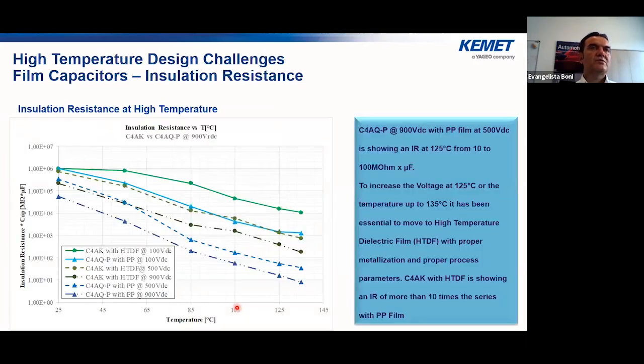Here it is possible to see also the insulation resistance behavior versus the temperature. Here we have the insulation resistance, and here we have the temperature on the axis. It's possible to see that all the lines are decreasing, so the insulation resistance decreases versus the temperature. Of course, when increasing the voltage, the lines show a lower insulation resistance.